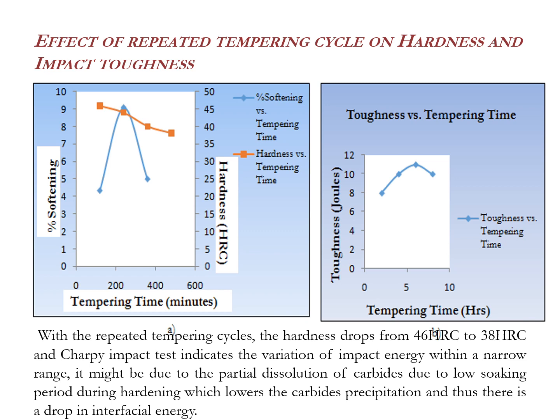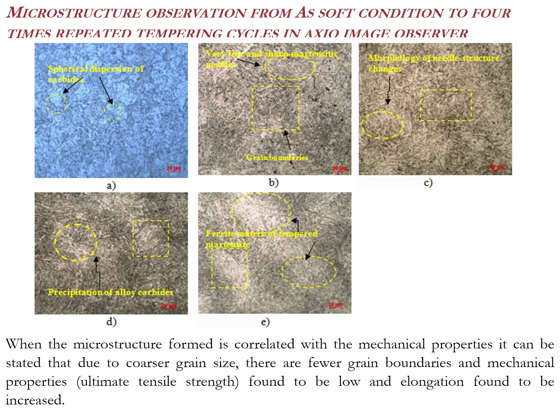Effect of repeated tempering cycle on hardness and impact toughness. With the repeated tempering cycle, the hardness drops from 46 HRC to 38 HRC, and Charpy impact test indicates that the variation of impact energy varies within a narrow range. It might be due to the partial dissolution of carbides due to low soaking period during hardening, which lowers the carbide precipitation, and thus there is drop in interfacial energy.